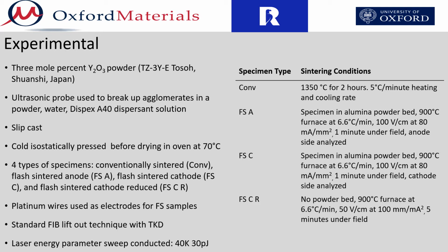Standard FIB lift-out techniques were used to create samples suitable for APT analysis, and transmission Kikuchi diffraction was employed to target and characterize features such as grain boundaries and triple points. Furthermore, a parameter sweep of laser energy values was conducted in order to optimize analysis conditions to achieve chemical compositions consistent with powder chemistry reported by the manufacturer.